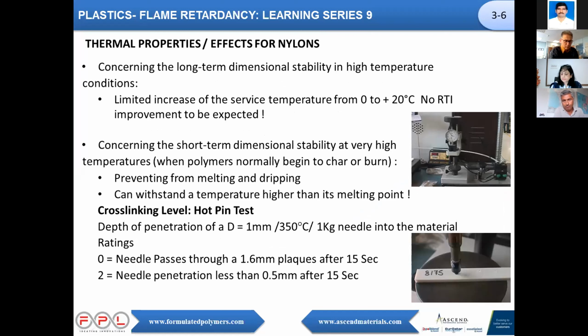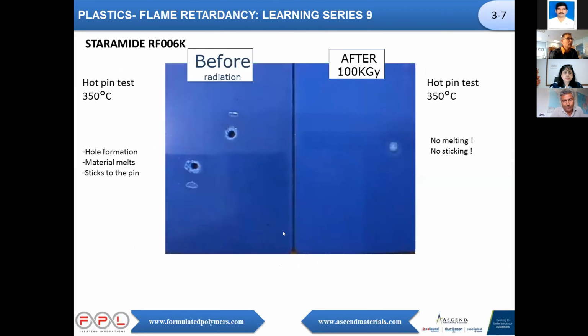So practically, how can we test that? How can we be sure that the material did react? Because basically you are not changing the shape, you are not changing the weight, you are not changing sometimes the color, you are just sending some parts outside and receiving them back. So for this, a very simple test is what we call the hot pin test. So basically you saw this pin, which is applied to a specimen under a load at a certain temperature. To make that short: 350 degrees C, 1 kilo, 1 millimeter, and you apply it to the part.